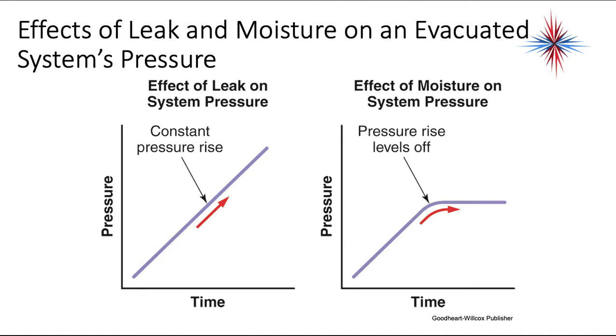So you can have leaks and moisture affect the evacuated system pressure. If you have missed a leak, what's going to happen is once you have evacuated the system down to your 500 microns, you shut off the vacuum pump, close your gauges, and you're going to see a consistent rise in pressure over time. That means there's still a leak in the system. If you have moisture in your system, which basically means you still have to run the vacuum a little bit more, you're going to see the pressure rise but then level off at a point higher than your target evacuation. So again, a straight slanted rise in pressure over time means you have a leak. If the pressure rises and levels off, you don't have a leak, but you still have moisture in the system. Watch your gauges and be able to identify this.